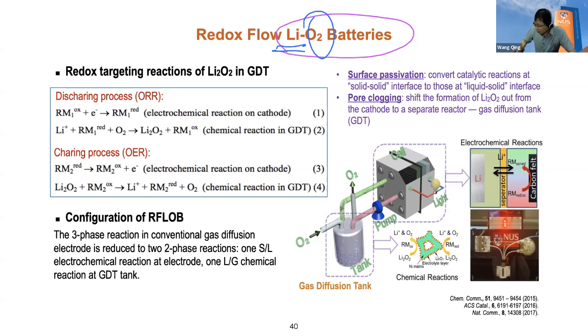The reaction product, the lithium peroxide, if you use aprotic organic solvent, is insulating and also insoluble. That means once it forms, it will cover the surface of the electrode, clog the pores and also passivate the electrode. So that makes the activity of the electrode drop quickly. That's one of the limitations I mentioned previously. The conventional electrolyte interface becomes very complicated. Based on the redox mediated process, we can shift this reaction from the electrode surface to a separate reactor tank.